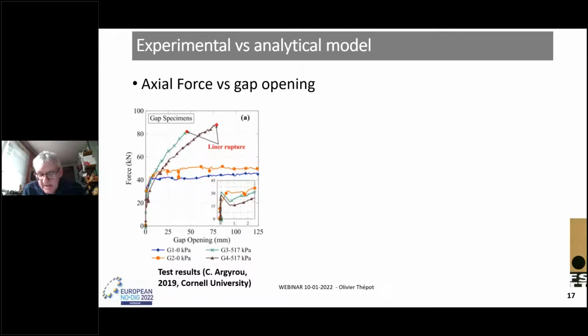The maximum opening gap, which is not visible on the graph, exceeds 200 millimeters. The other 2 tests, the green and the other one, were carried out with an internal pressure of 5 bars, 0.5 megapascal. It can be seen that the tensile force increases rapidly with the gap opening until failure, here and here, which is reached at around 80 to 90 kilonewton for an opening of 45 to 80 millimeters, respectively.